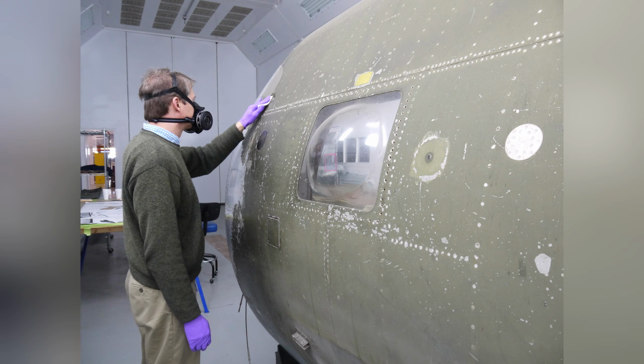The method fingerprint for this operation is controlled overpaint removal on the nose section. Physical scraping or abrasive blasting is not the governing approach, because any uncontrolled mechanical action could damage the original paint, the graphite markings, and the wartime wear directly below. The team maps the areas of later overpaint through archival evidence, normal light photography, ultraviolet imaging, infrared reflectography, material analysis, and solubility testing. Conservators then use carefully tested organic solvents and controlled application methods rather than broad chemical washes.